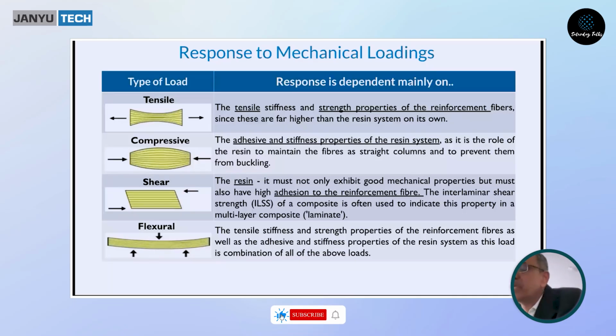If you take a typical SMC or resin material, the tensile modulus is generally 3 GPa, whereas the tensile modulus of e-glass filament is 72 GPa. And the tensile strength of the resin is 50 to 60 MPa, whereas the tensile strength of glass fiber is many times higher than this. So in a composite combination, fiber plays the dominant role in determining the strength and stiffness of the composite material.